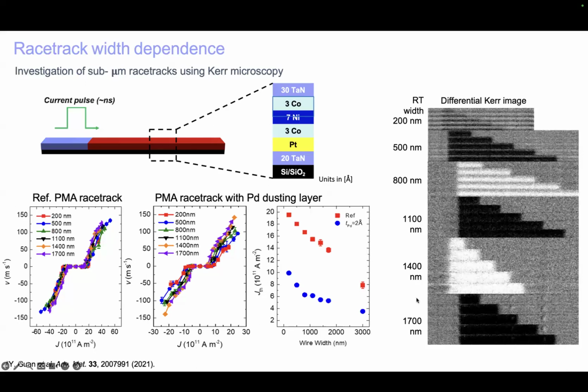from 1700 all the way down to 200 nanometers wide, where we can still detect the motion of a domain wall, but very poorly. And then what we found, which was a surprise to us, is that the velocity of these domain walls varies very little with the width, for the same current density.